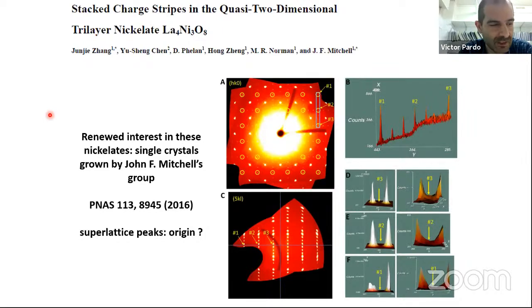What he did was he could get single crystals of this lanthanum 4 nickel 3 O 8, and what they saw was that with the single crystals they could measure much better the structural properties of this compound than with the powder that was available 10 years before. And what they saw was that there were additional superlattice peaks at low temperatures. So what was producing the low temperature insulating state was some kind of a structural reconstruction.